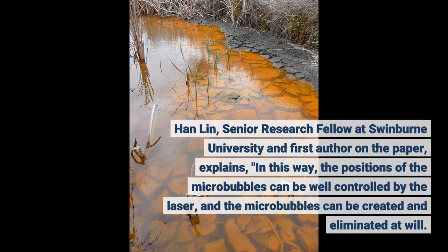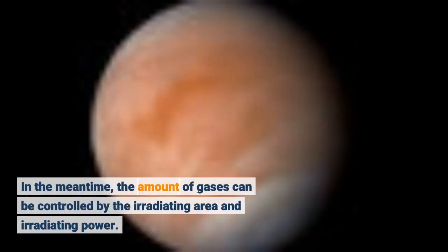Han Lin, senior research fellow at Swinburne University and first author on the paper, explains, in this way, the positions of the microbubbles can be well controlled by the laser, and the microbubbles can be created and eliminated at will. In the meantime, the amount of gases can be controlled by the irradiating area and irradiating power. Therefore, high precision can be achieved. Such a high-quality bubble can be used for advanced optoelectronic and micromechanical devices with high precision requirements.